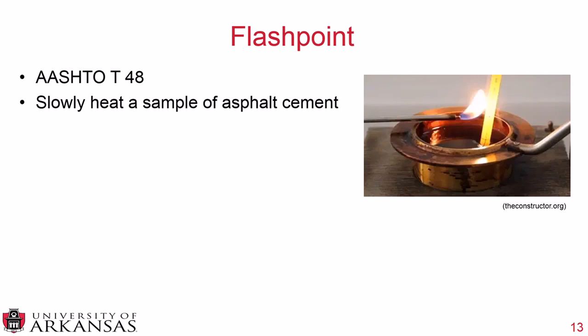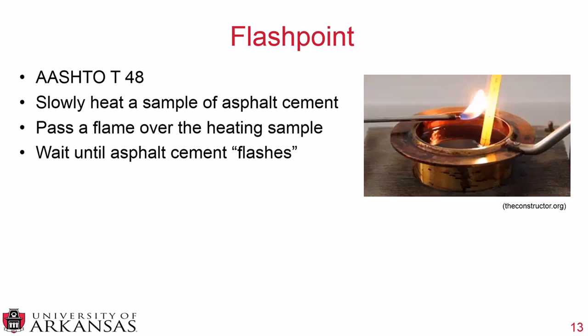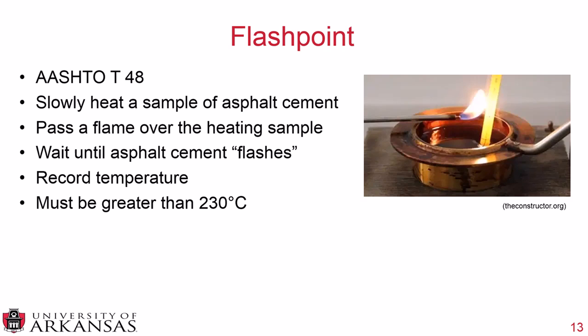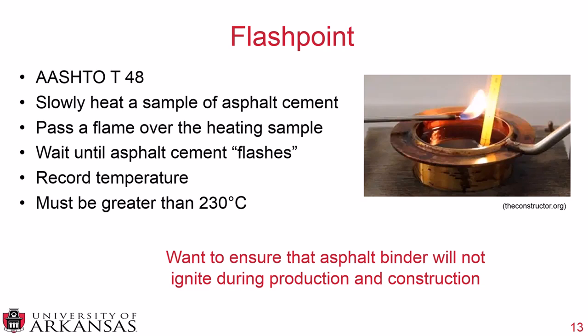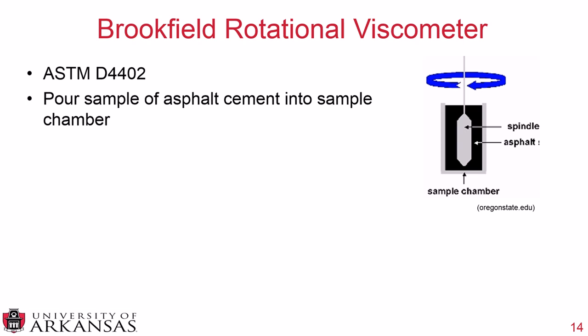The Flashpoint test (AASHTO T48) slowly heats a sample of asphalt cement while passing an actual flame over it until the sample flashes. The recorded temperature must be greater than 230°C, giving an indication of how volatile the different components of the asphalt binder are. The whole point is to ensure the asphalt binder will not ignite during production and construction, reducing the risk of fire at an asphalt concrete plant.